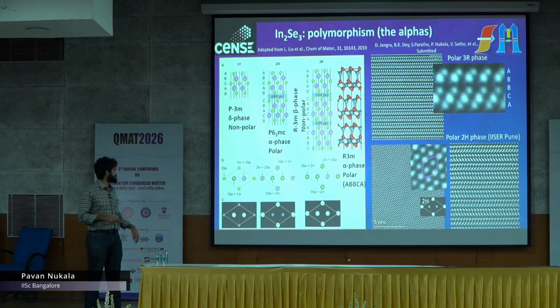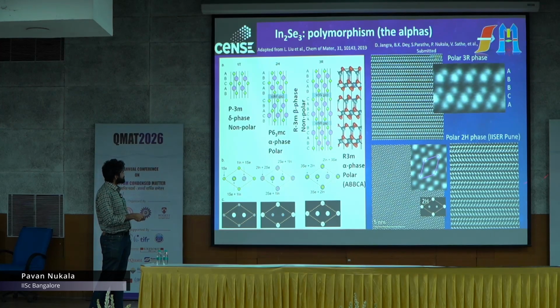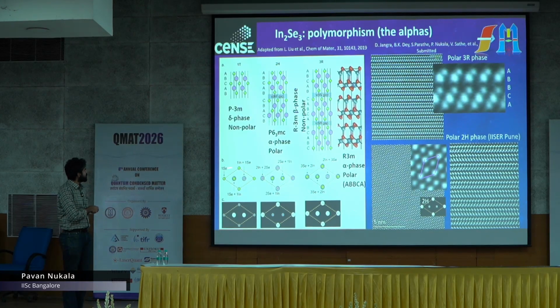Again, a hexagonal arrangement. This is the cross-sectional view, where you see these nice van der Waals layers. But if you look at this in plan view, you have a unit cell that is also separable, right? For example, the T phase, this is not very clear here, has larger atoms sitting here and smaller atoms sitting at the corners of the unit cell. The 2H phase has a reversal of contrast. So using this sort of atomic contrast, I'm going to distinguish between these phases moving forward.